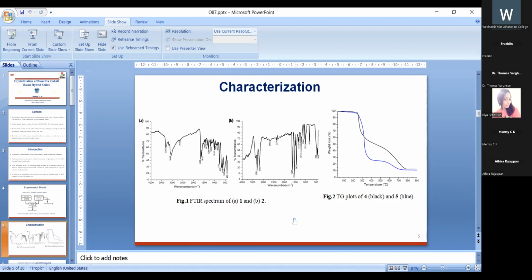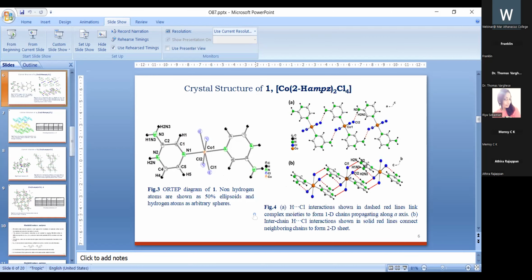The obtained solids were characterized by single crystal XRD and FTIR. The thermal stability of the solids was studied by thermogravimetric analysis. From the single crystal data, it was observed that in the crystal structure of 1, Co2+ is at the center of the octahedron, surrounded by 2 protonated aminopyrazine moieties and 4 chloride ligands.